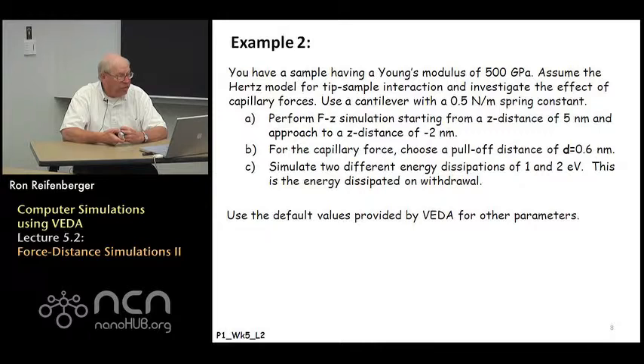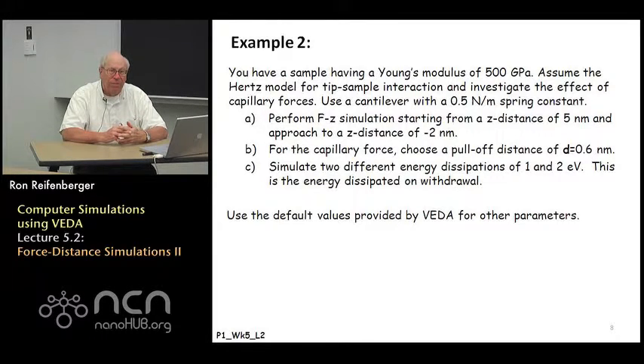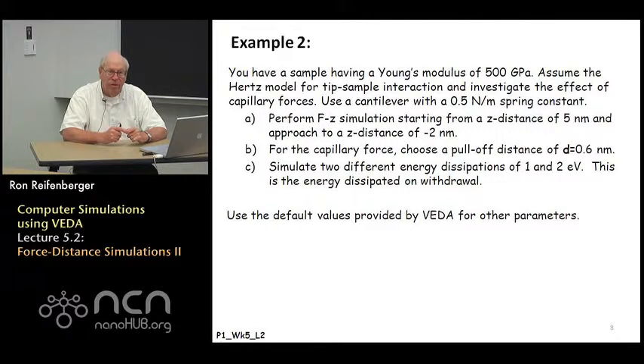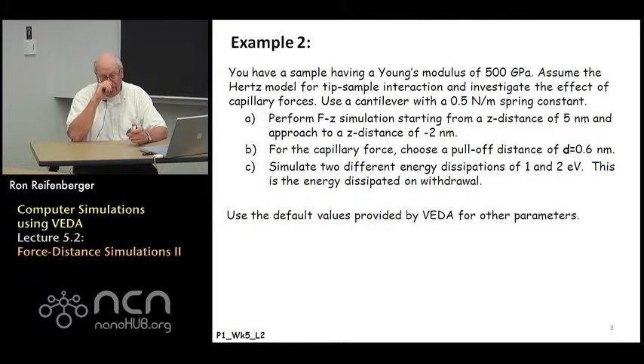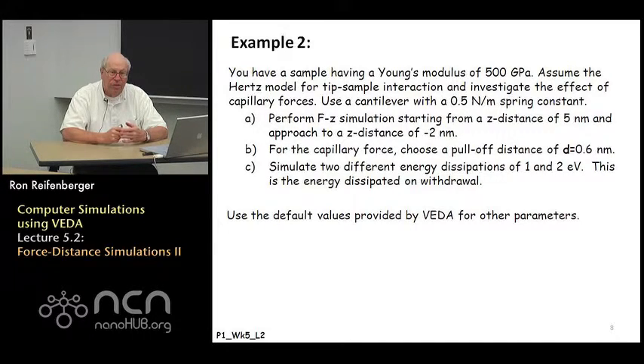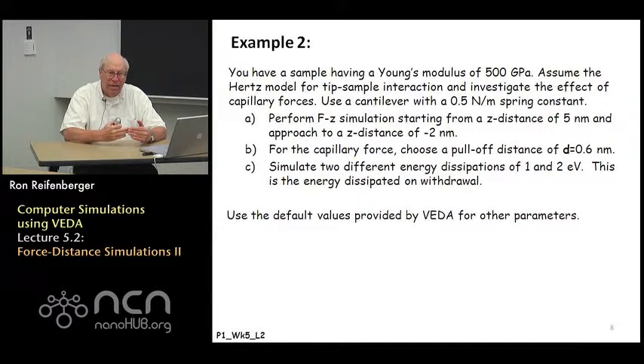Here's another example: selecting the Hertz model for contact. Recall the Hertz model is most appropriate when tip-substrate interaction potentials are negligible and both the tip and substrate are hard, so that deformation is specified by the Hertz model rather than the DMT. In this particular case we select a spring constant of about half a Newton per meter, performing force versus distance simulations from plus five nanometers to minus two nanometers in Z. We're going to include the capillary force model for the interaction between the tip and the substrate.